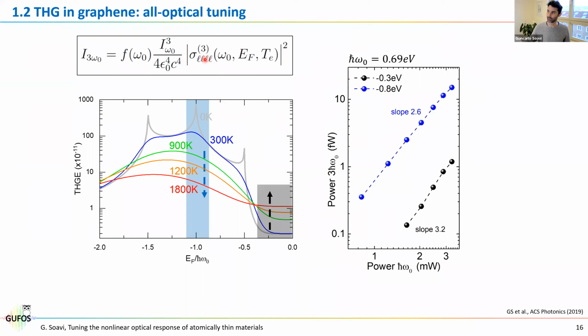But since sigma 3 depends on the electronic temperature, as we scan the power, we must also see a dependence. So we should also see a different slope of the third harmonic generation intensity that sums up to this cubic dependence. So if we are close to the zero Fermi energy, so the black curve here, as we increase the power, we increase the efficiency, and the slope should be larger than 3. If we are at large values of the doping, as we increase the power, we decrease the efficiency, and the slope should be smaller than 3.